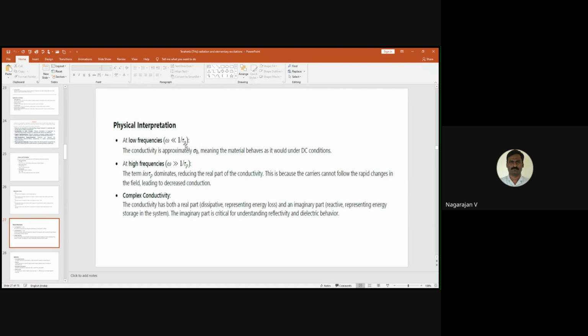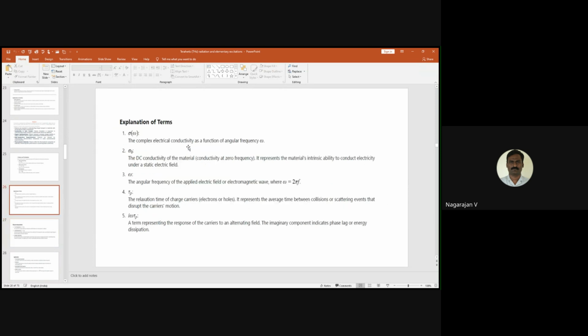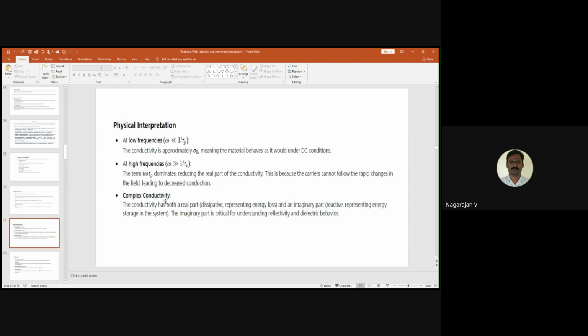Tau p indicates the relaxation time of charge carriers, the average time between collisions or scattering events that disturb the carrier motions. When omega tau p is less than 1, the material behaves as it would under DC conditions. If omega is greater than 1 by tau p, the carriers cannot follow the rapid changes in the field, leading to decreased conduction.